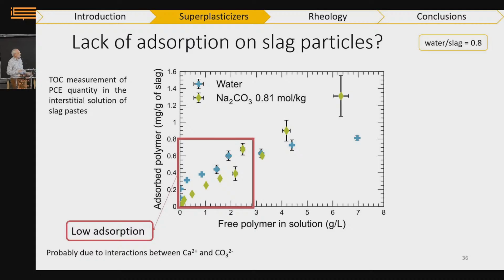Again, we have no direct proof of that, but we know that calcium and carbonate form strong ion pairing in solution, just like with sulfates. And probably this has to do with the adsorption of the polycarboxylate ether, which is anionic at high pH, being mediated by the calcium that adsorbs on the surface and inverts the charge of the cement grain or the slag grain. If this calcium is mobilized by carbonates, we can understand that it won't be able to attract electrostatically the carboxylate ether, our superplasticizer.